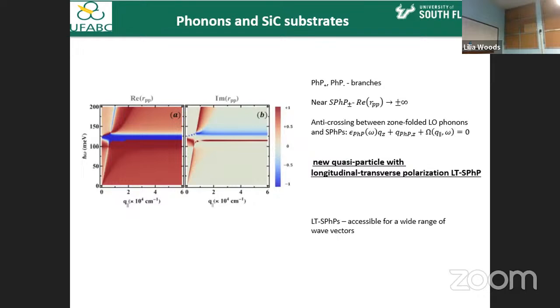And we also discovered a new type of phonon. And this new type of phonon is a peculiar one. It has a mixed longitudinal and transverse polarization. And this new type of phonon polariton is only present in specific polytypes. It does not exist for all types, only specific polytypes, so there's a peculiar form. We'll get some details. And by the way, this new type of phonon polariton, we call it longitudinal transverse surface phonon polariton. And you can see it here, these flat lines here and here. The peculiar thing about this phonon polariton is that it is accessible to very large wavevectors. By the way, there's already some evidence.